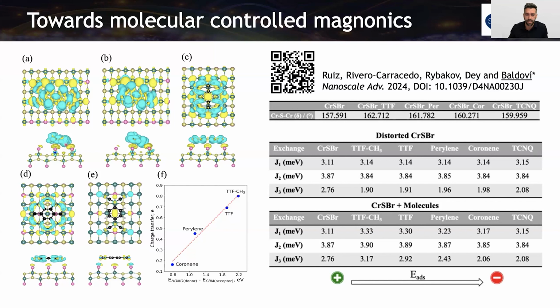In this case, with TTF-CH3 and TTF, the molecule is bent towards the substrate, as I said before. And then coronene and perylene are also donating, and the acceptor, the TCNQ, is not providing any kind of charge transfer. When we plot here the calculated charge transfer for these molecules, there are these blue dots, and we compare with the energy of the HOMO of each one of the molecules in gas phase with the conduction band of the chromium sulfur bromide.